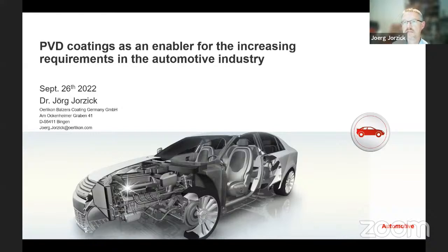So there are different types of philosophies in the market. Some are using filtered arc processes, but then the deposition rate is going down because you have this filtering device, and depending on how much you filter, you get a smooth coating, but it will grow very slowly. Or you do it fast with a lot of droplets, and then you have to put more effort into the post-treatment. So we have both technologies, filtered and unfiltered, in Oerlikon, and depending on the application, we rather use one or the other. But really, for the arc evaporation process, you have to do either this filtering or the post-treatment in order to create a stable tribological system and not to destroy the counterbody.